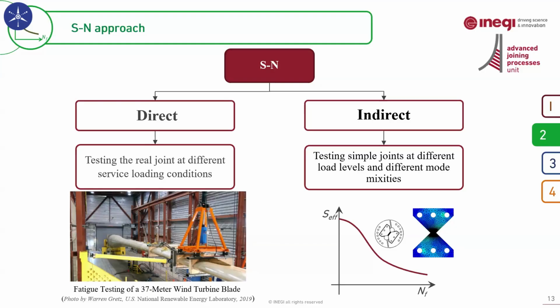So it's an expensive test and requires specialized equipment and gripping systems. But the good point here is that it doesn't rely on simplifying assumptions, and it captures the actual fatigue life of the bonded joints. However, the direct method doesn't actually characterize the adhesive itself. Instead, it only evaluates the fatigue performance of that specific joint within that particular structure. So as a result, the findings are limited to this specific application, and we cannot use the data or the results for other joint geometries or in other structures.